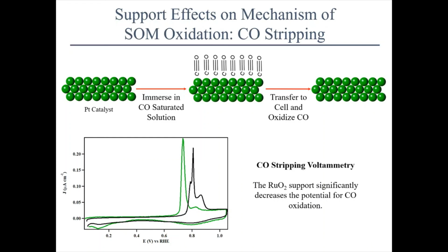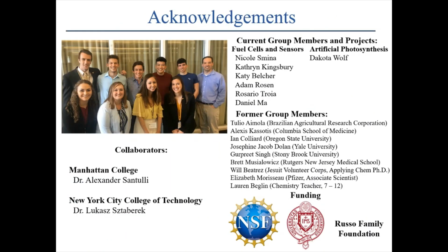So this showed us that not only are we getting the SMSI effect, which is that slight shift in the platinum down by about 41 millivolts, where the platinum gets a little bit easier to oxidize, but we're going beyond that. To get to 100 millivolts, we must be getting some effect from the oxygen coming from the ruthenium oxide itself, leading to enhanced CO stripping. So in essence, we're making it much easier for platinum to remove that poisoning intermediate.